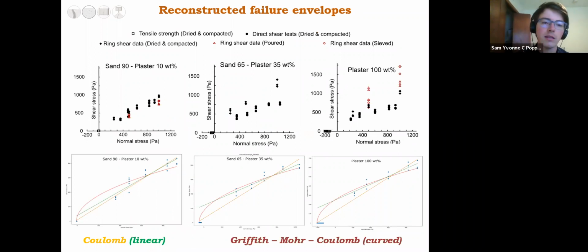We basically constrain that normal stress on the horizontal axis versus shear stress space for our materials, and then applied a simple linear Coulomb criterion and a combined curved Griffith-Mohr-Coulomb criterion, which is red in the bottom diagrams, to try and constrain the cohesion of the materials, which is the intercept of these regression curves or interpolation curves with the vertical shear stress axis.